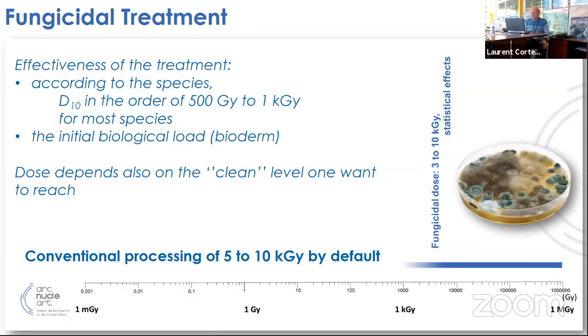Talking about microorganisms and fungi, it's not exactly the same. The death will come in probabilistic manners. For most species, doses between 500 gray and 1 kilogray will kill 90% of the population. It is called the D10 lethal dose. This is the dose that leaves 10% of survivors. If you irradiate again with the same dose, you will kill again 90% of those survivors. So you will get only 1% of survival.